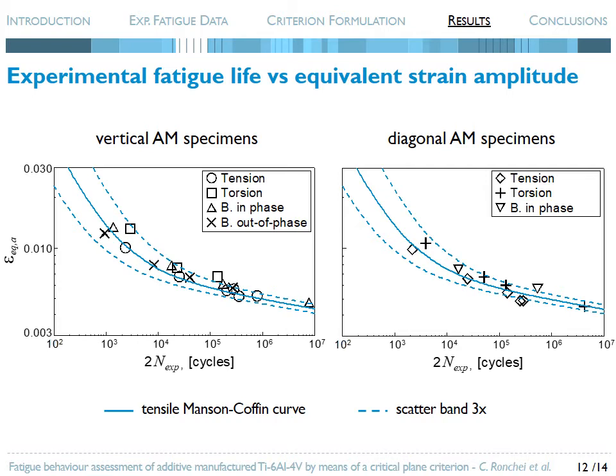According to the fatigue criterion here employed, the present figures show the experimental fatigue life, N_exp, plotted against the equivalent strain amplitude for vertical and diagonal AM specimens. The blue solid curves are related to the experimental tensile Manson-Coffin equations. A good agreement between experimental and theoretical data is in general observed, since the theoretical results lie very close to the experimental curves, and this holds true independent of the specimen build direction, in accordance with experimental outcomes.